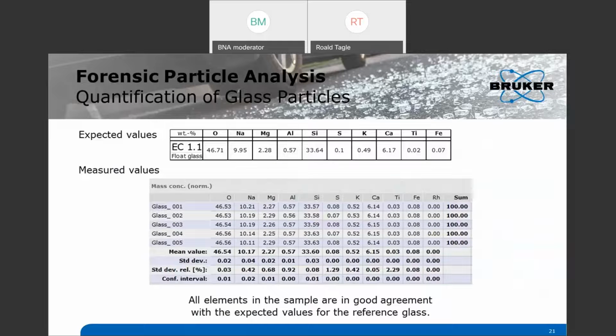So basically, we did this first validation of the method for known reference materials. Then we look at the material to figure out if the particles are representative of the large sample of glass. This is again still a validation, but this is the reference glass, and we're at the moment just working with composition. You see that our values are in very good agreement with the expected values for the reference glass, so basically the composition values are very reliable.